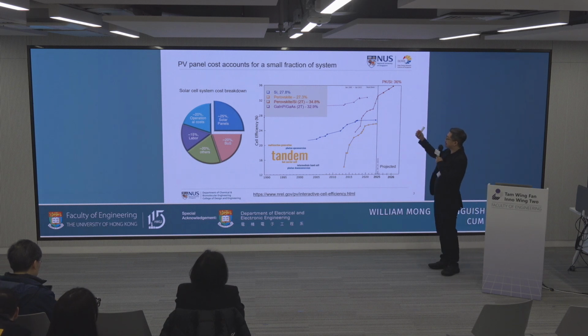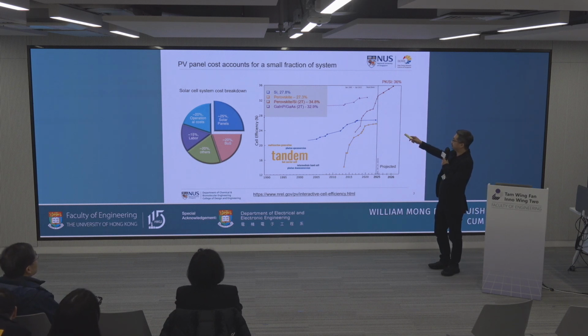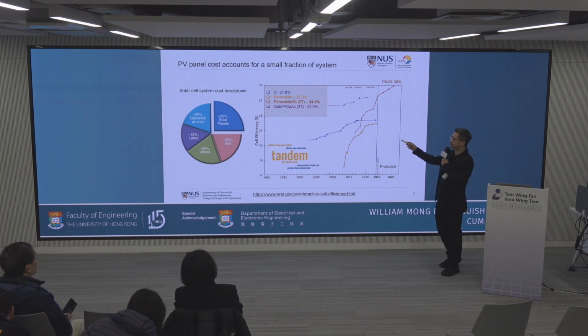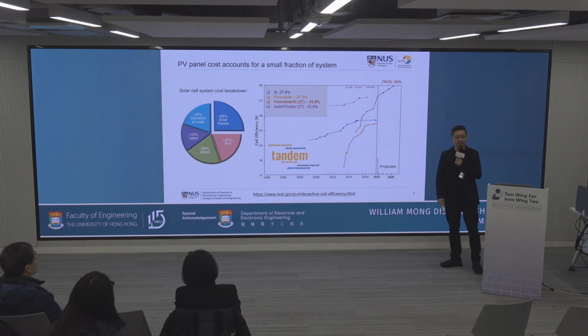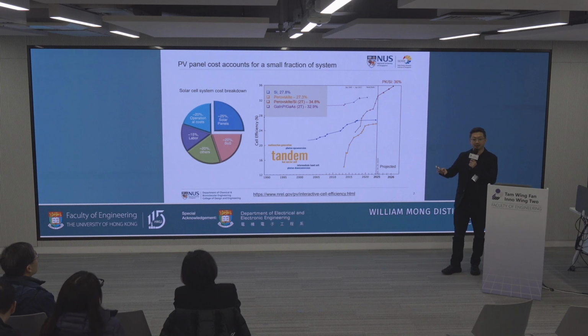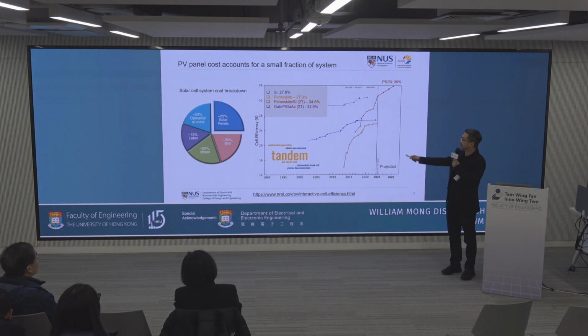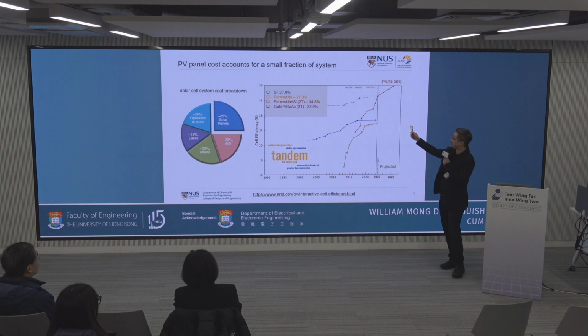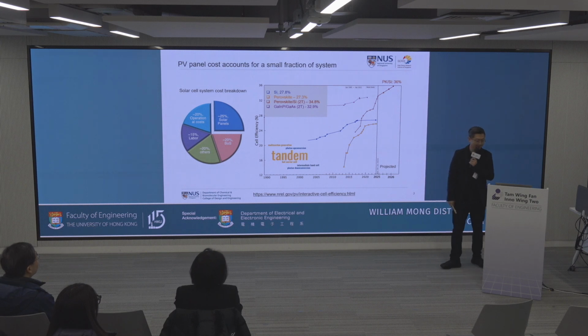So if you look at this chart, you can see we have the perovskite single junction and the silicon single junction. Actually, both of them reach this 27% region, so efficiency-wise, it's quite comparable. But in single junction, we want to break this so-called SQ limit, and we make the tandem. In tandem, we put the perovskite on top of the silicon. You can see right now it's not updated. Actually, it's 35% already. Recently it was announced by Longji.